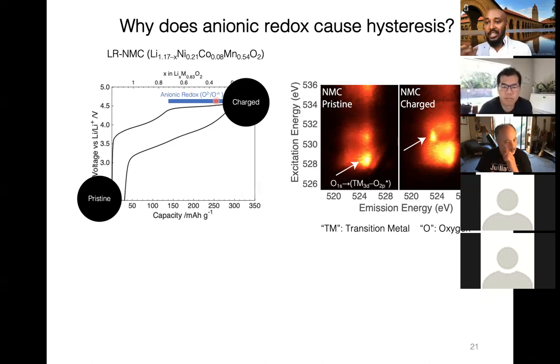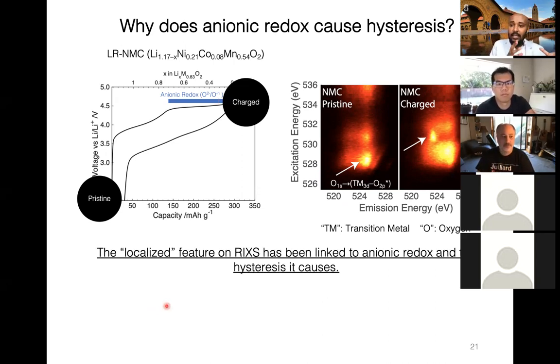Since we commonly see this feature whenever we have anionic redox, in the field we have been correlating this feature with anionic redox. So the hypothesis is, since anionic redox causes hysteresis, or is correlated with hysteresis, and since this feature is also correlated with anionic redox, can this feature tell us the mechanism of anionic redox, and also why we have hysteresis?